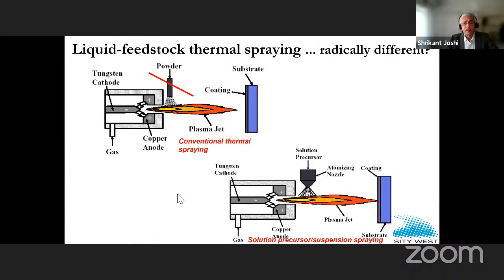This use of liquid feedstock, is it radically different? Depends on perspective. So there is a very simple cartoon of what a conventional plasma spray process looks like. You have this plasma spray torch, there's a powder that you introduce radially, and all the heat up and acceleration happens as we spoke about a moment earlier, right? When it comes to liquid feedstock, the only thing that really changes is that the powder delivery is replaced by a liquid feedstock delivery, right?